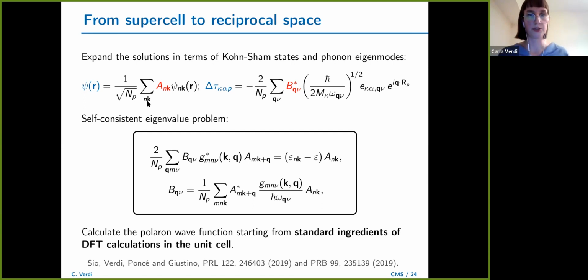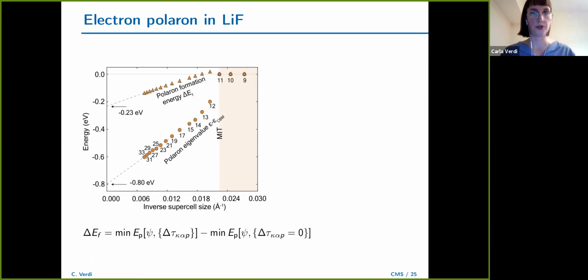You see these summations over k and q. These k and q are reciprocal space wave vectors. And so the reciprocal space wave vectors will basically mimic the supercell. So if I do a summation over a grid of 10 by 10 by 10 wave vectors, this is equivalent to a 10 by 10 by 10 supercell, just as an example. So let me show you some results to convince you about what we're doing, really.